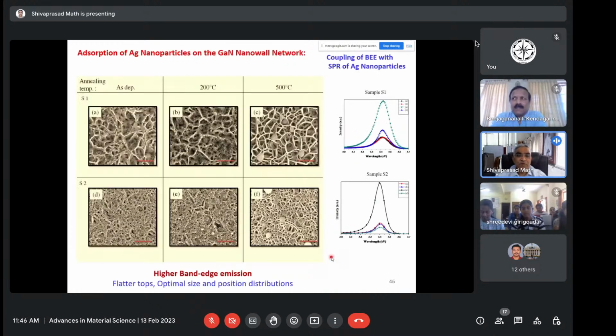Okay, if you remember, I also talked about plasmons. If I can make nanoparticles of metals sitting on a surface and excite the electrons inside that material, the plasmonic energy gets stored in that nanoparticle. Now, if I give another radiation to that, they can couple together and form an enhanced radiation. I think this coupling of the plasmonic energy with the band gap's released energy was something we wanted to try. So we put some silver nanoparticles on this.